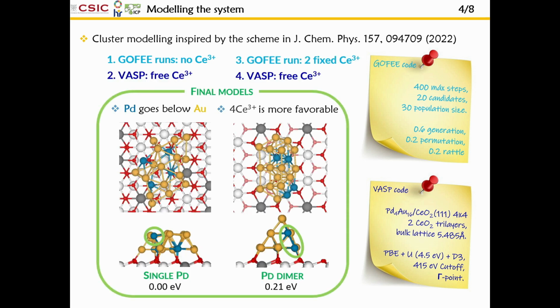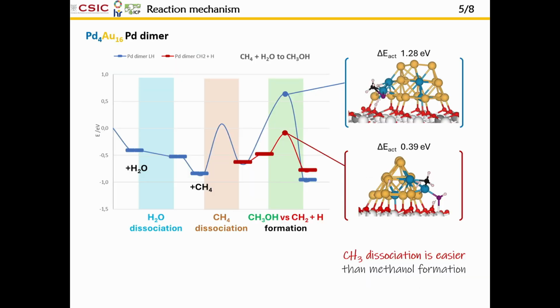But eventually, we found that most of the structures, in agreement with the experimental as well, the palladium atoms get covered by gold, and you have very few atoms accessible. So in this one, this is the most stable structure. You only have one, and it's the one that you obtain in most of the structures. But we manually selected another more unstable structure to compare with it, that has two palladium atoms accessible, forming a dimer. And with these two models, we studied the reaction mechanism, and I don't have time in 6 minutes to tell you everything about it, but one key result is